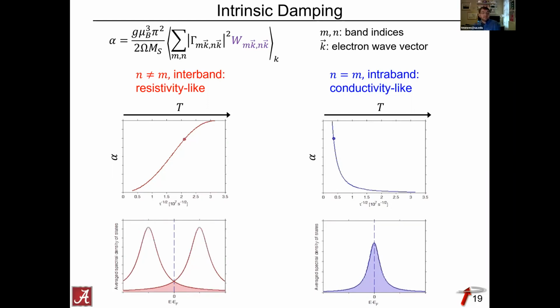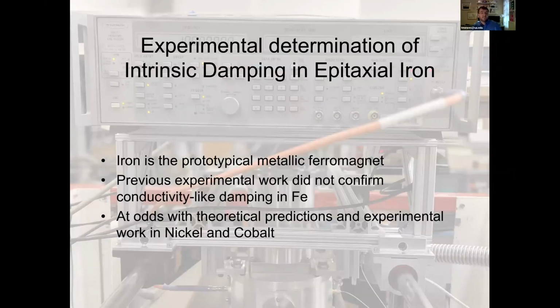So quite a while ago, together with Satoru Emori, we noticed that there's actually something missing in our understanding of a very simple ferromagnet, which is iron. You would think iron is the prototypical metallic ferromagnet, so everything is known about it. But if you look at the model that I just discussed, there should be a term that scales like the conductivity. But all experiments up until that point did not really confirm the existence of this kind of contribution.